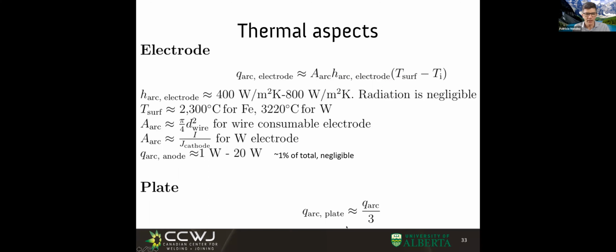And then on the plate, we have something that is a lot simpler that I hope to get better at some point, but this is something that gives us good numbers. The power in the arc is current times voltage, right? And for example, an arc of 3 millimeters in TIG would be 3 volts. And if we are running that at 100 amps, it would be 300 watts, right? And what we're going to assume is that 1/3 of the arc energy goes to the plate. It would be like 100 watts from that arc goes into the plate.